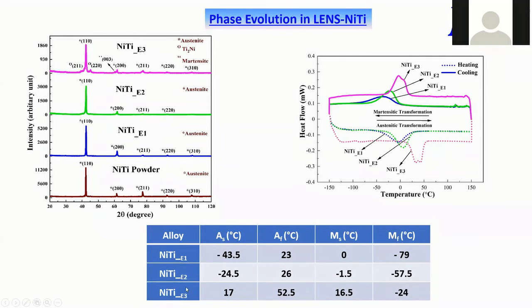You can see that the one prepared with the highest energy density has quite a high value of austenite finish temperature, 52 degrees centigrade, which means that this alloy might not be fully austenitic at room temperature. Okay, if we want to use it at room temperature, we may not get the complete pseudoelastic recoverability in this